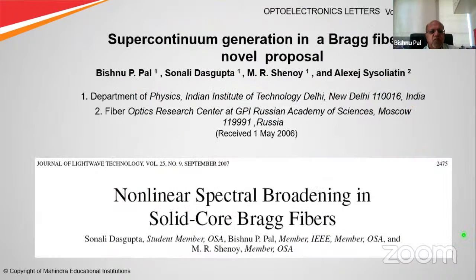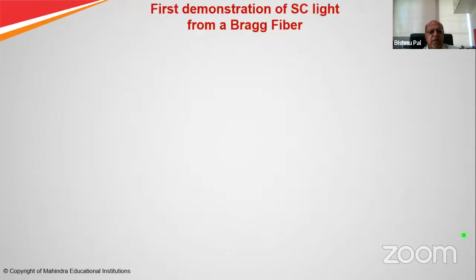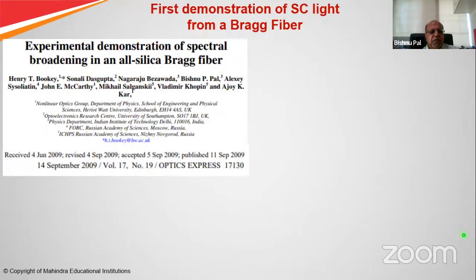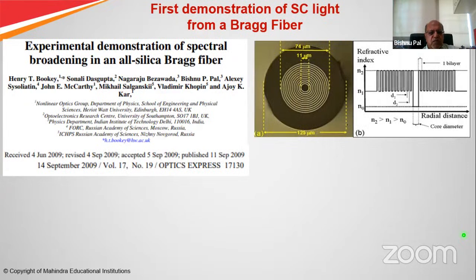So we did some work. We did quite a bit of work again on nonlinear Bragg type of fiber, and demonstrated for the first time supercontinuum light from a Bragg fiber, in an experimental collaboration with Russian scientists at the Russian Academy of Science. This is our design that we shared with our Russian colleagues. They fabricated it. You can see the concentric alternate dark and bright rings corresponding to different refractive indices.